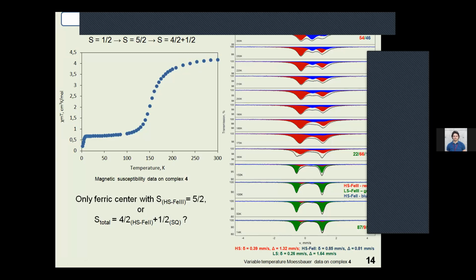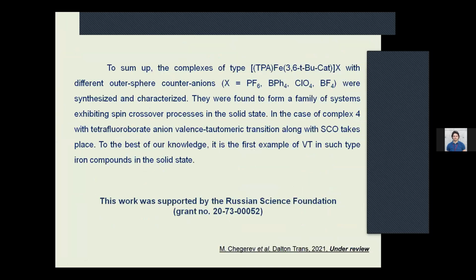This finding, to the best of our knowledge, makes compound 4 the first ferric catecholate system of this type demonstrating valence tautomeric transition in the solid state alongside the spin crossover. To sum up, complexes of type TPA iron catecholate with different outer-sphere counterions were synthesized and characterized. They were found to form a family of systems exhibiting spin crossover processes in the solid state. In the case of complex 4 with tetrafluoroborate anion, valence tautomeric transition along with spin crossover takes place. To the best of our knowledge, it is the first example of valence tautomerism in such iron complexes in the solid state.